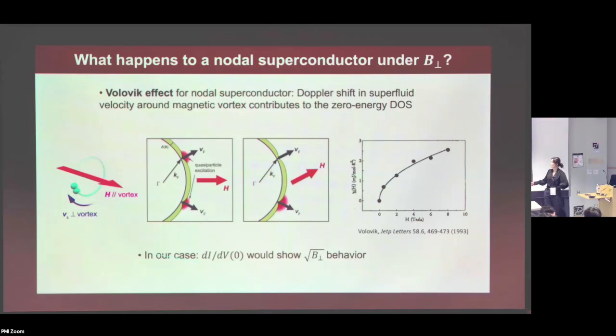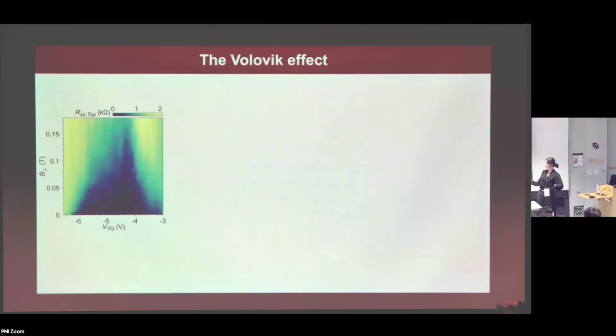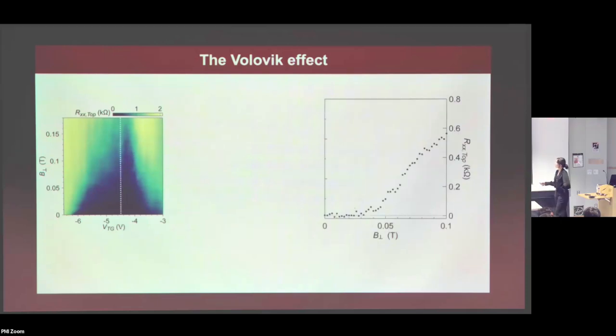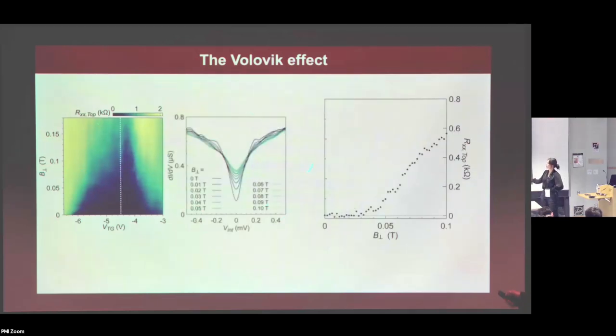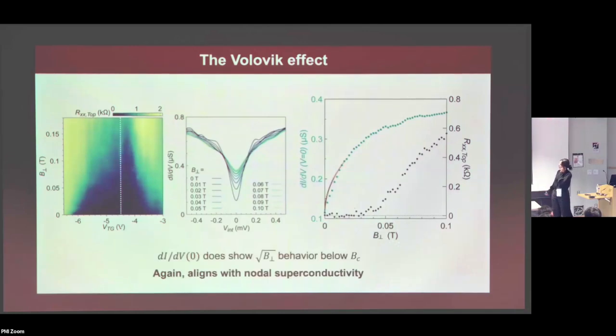So what this tells us is that in our case, if you have nodal superconductivity, the Volovik effect will result in the zero bias conductance having a square root of B perpendicular behavior. That's the expectation, and we can see what happens. This is the transport superconducting dome as a function of out-of-plane magnetic field. You can take a line cut at some optimal doping and look at what happens in the tunneling curves. We can track that zero energy density of states and plot it as a function of B perpendicular. You can see that up to around BC, as measured in transport, this trend fits the square root behavior, which again aligns with the nodal superconducting gap.